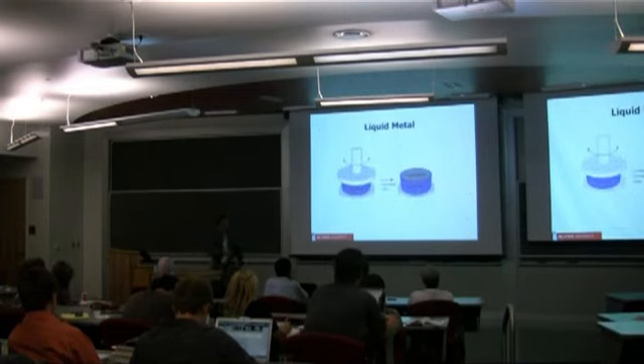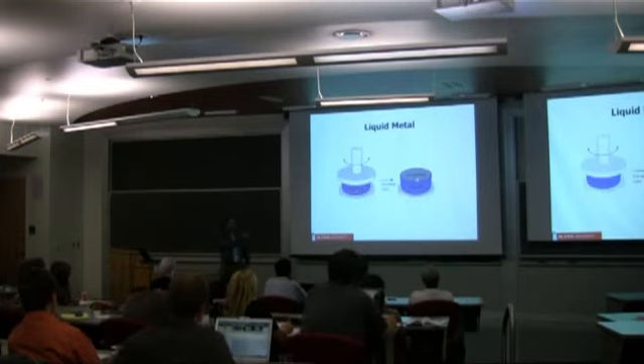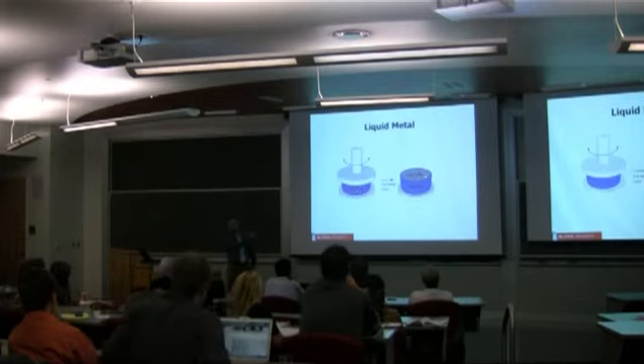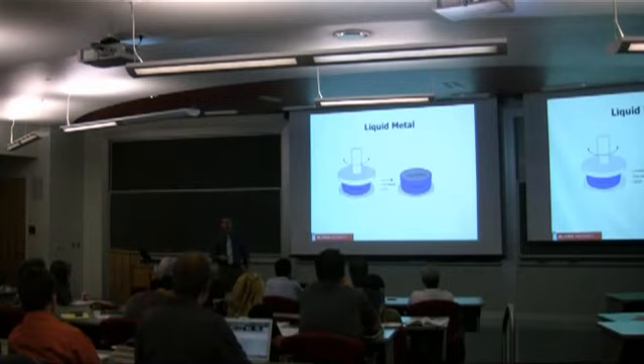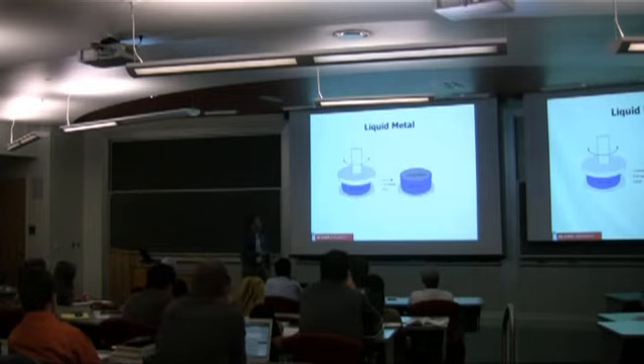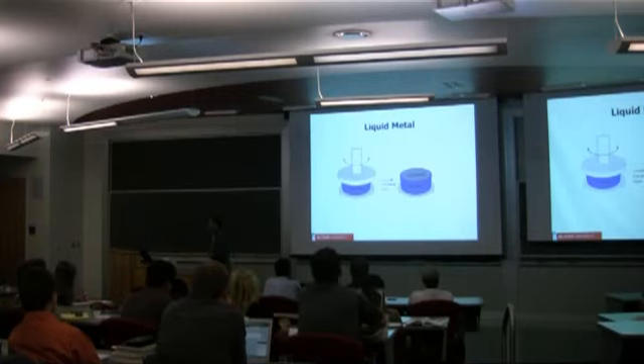And if you take your Oreo cookie, so here's the liquid metal, and you do a cross-sectional view, the bulk of the material is a low viscosity liquid. And so from the rheometer standpoint, it can't even tell that it's there. The viscosity is so low. And so what you're really measuring is the mechanical properties of the skin which surrounds the fluid.